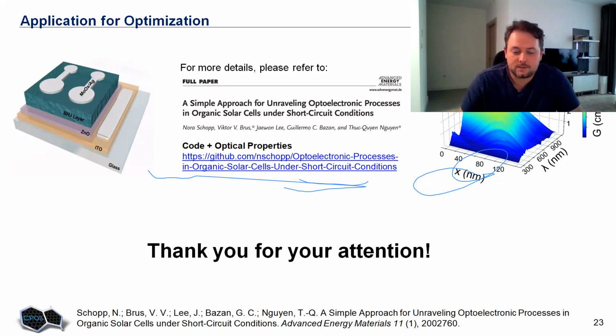In terms of stability, obviously there are some issues. They are not as stable as silicon because they are organic layers. And it also matters if you apply some filters for UV light, which is not so much in the solar spectrum. If we block this UV light, then it will not reduce the photocurrent a lot. However, it will significantly prolong the stability of these devices. Nowadays, there are products available on the market which provide a warranty for the T80 time. The so-called T80 time is the time during which the performance of solar cells drops from 100 to 80% of initial performance.